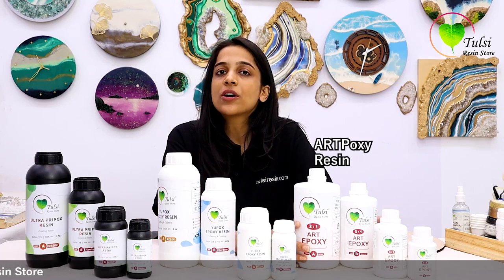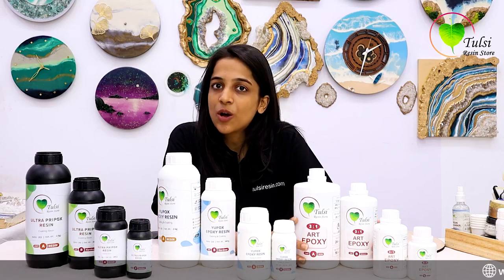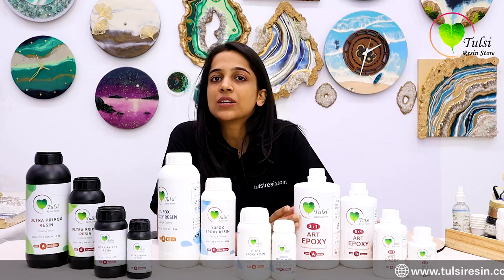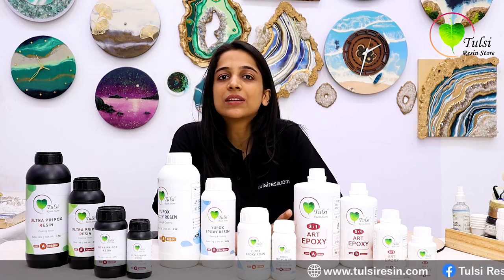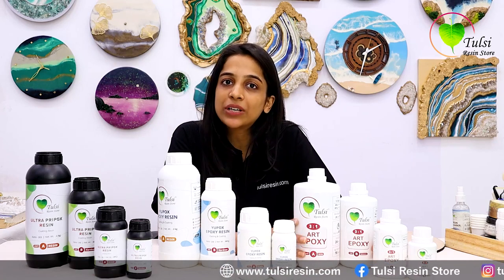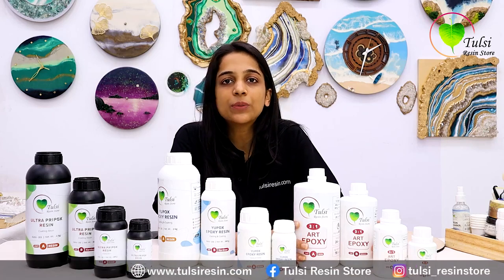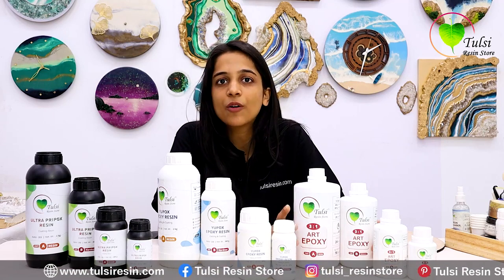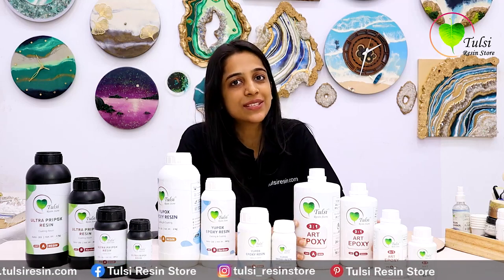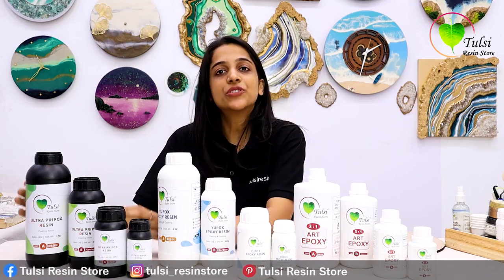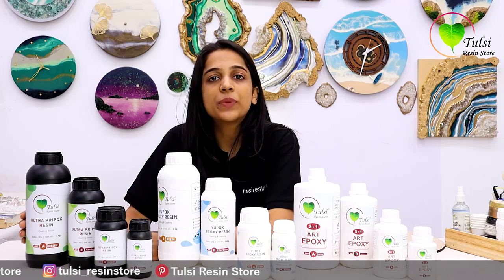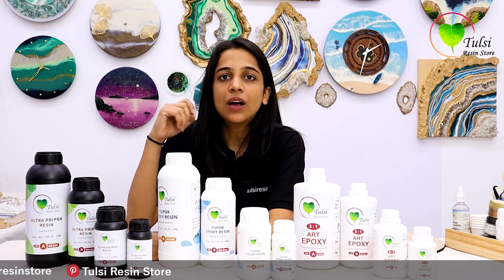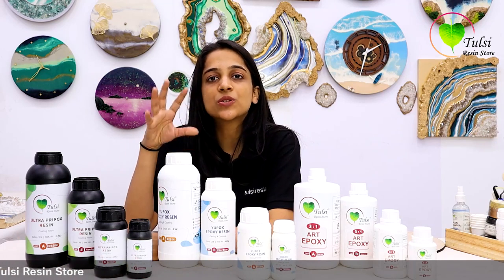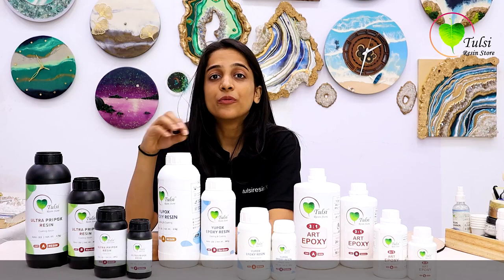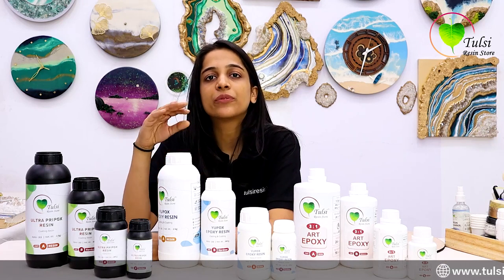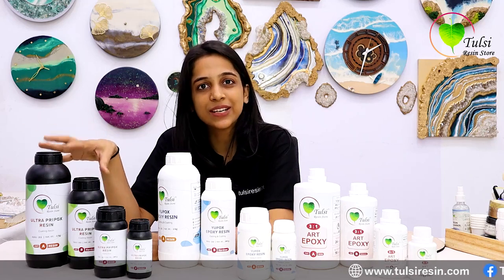And now the art epoxy resin, casting purpose in silicone molds. Whether the silicone molds are small or big, you can use this resin. You can use it for river tables, for your coffee tables, flower preservation, or anything with a thick cast. You can use this resin. Now, for the geode artworks, where you want your piece to have that limited artwork, you need your resin to stay where you pour it, with the thick viscosity, with the dome structure, and with high gloss finishing. You can use this resin.